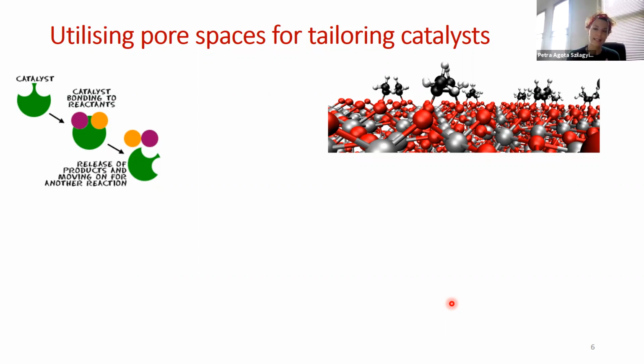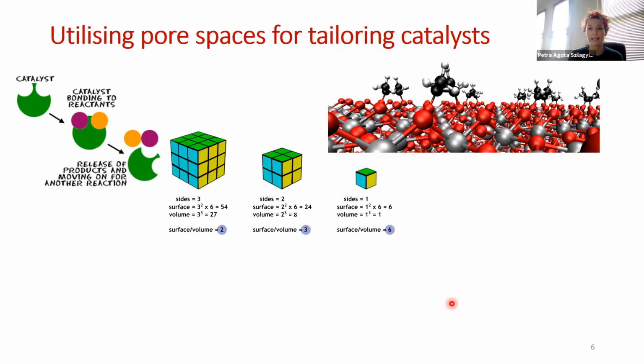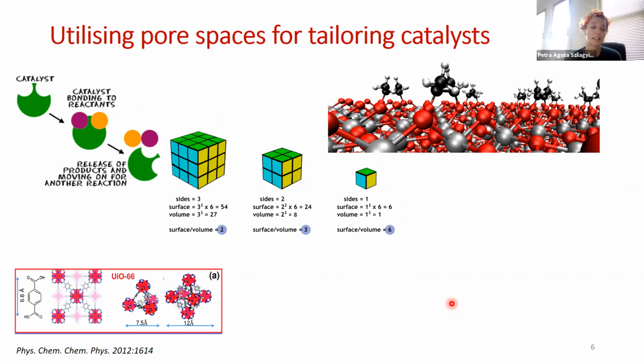And so what we can do is use it kind of as an inverse space as a mold to grow the nanocatalyst inside. What that means is that we will increase the surface to volume ratio of these nanocatalyst guests inside the pores of MOFs, or maximize the proportion of surface atoms in them. Let me give you a concrete example of a metal organic framework, and this is the one that I will be talking the most about today. So this is UiO-66. It's actually one of the most stable frameworks. It's built up of zirconia-like clusters.